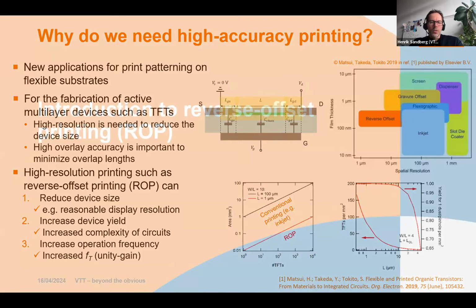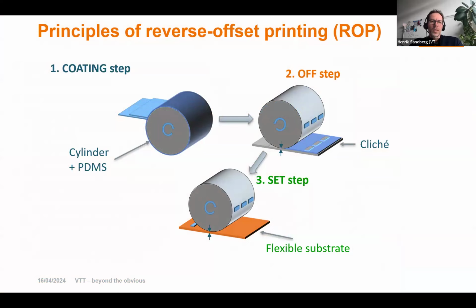So more details about the process as such. It has, as the name suggests, several steps. So it's an offset type printing method. First we apply a continuous film of our material, our ink, in the coating step. This is coated onto a cylinder with a PDMS film on top, and the properties of the PDMS film are very strict. So it has to have exactly the required properties, and we also make these PDMS films to work together with the ink and the coating process.